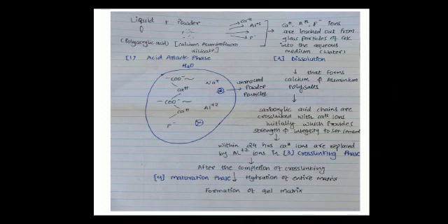After 24 hours, these calcium ions are replaced by aluminum ions in the cross-linking phase. After the completion of the third phase, the cross-linking phase, the hydration of the entire matrix is called the maturation phase, which forms the matrix gel.